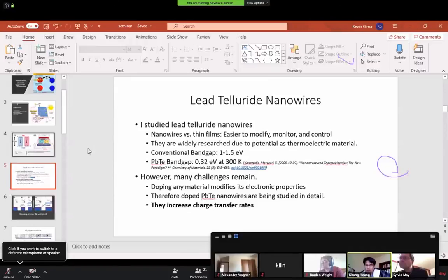Without spin-orbit interaction, you significantly overestimate the band gap. If you include spin-orbit interaction, which you should because the spin-orbit effect is very strong, then your band gap value is going to be underestimated. So it depends on how you do the calculation.